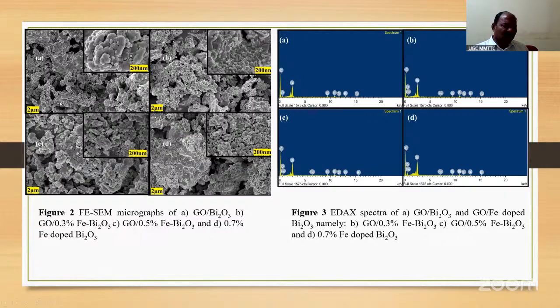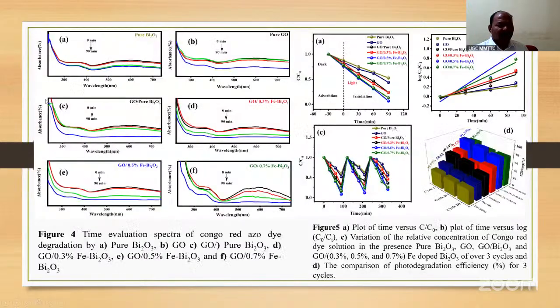Now you see these are the micrographs of the as prepared material. Now these are the time evolution spectra of Congo red azo dye degradation, the photocatalytic activity of pure and this one, then the plot of time variation of these materials. The plot of time versus log variation of this one, the cycles and all these we calculated.